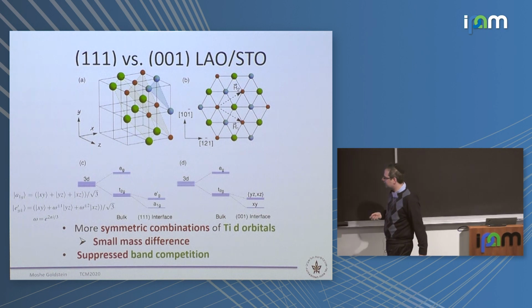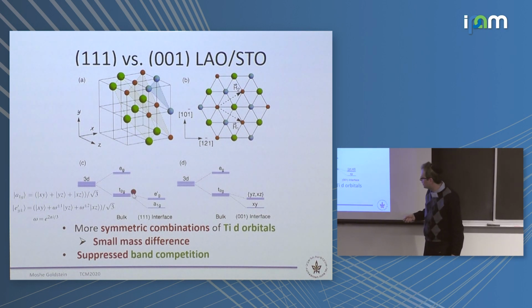So the important thing is that when you look at the t2g orbitals and you put them at the interface, now they don't split as XY versus YZ and XZ, but they split as A1g and Eg prime.